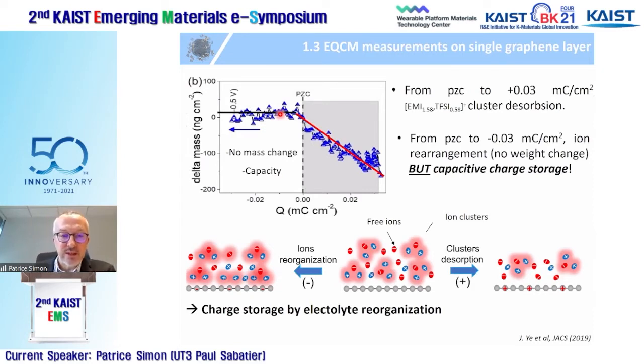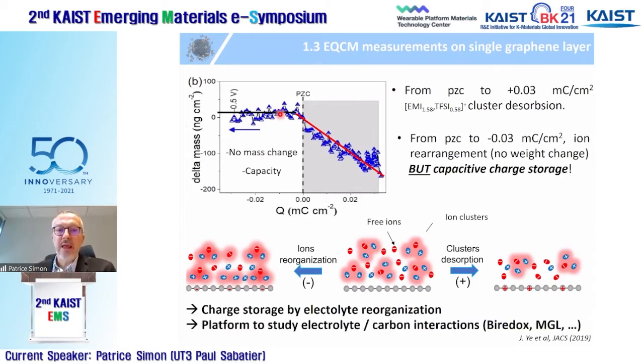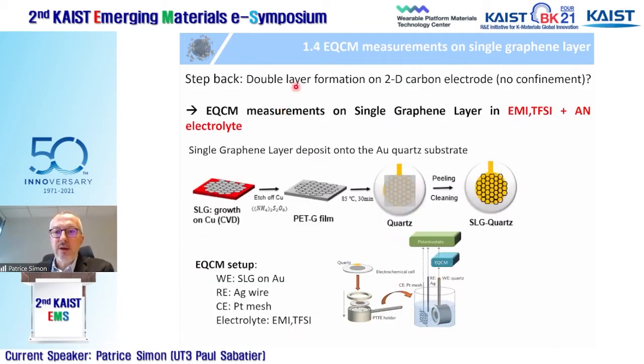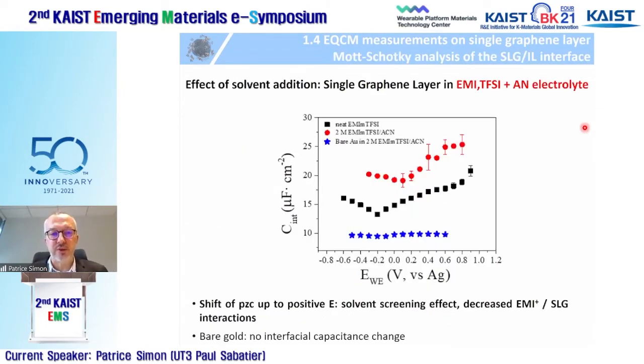So this was a very interesting result showing that, yes, you can have charge storage just by electrolyte reorganization. And these results are interesting because they offer a way to study the influence of electrolyte composition and so on. And then this is what we did in the next step. We still use a single graphene layer coated onto a quartz of EQCM. But now, instead of using EMI TFSI, we added a solvent, acetonitrile, CH3CN. And we study the influence of the presence of a solvent.